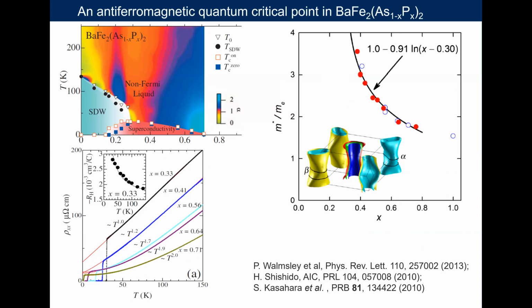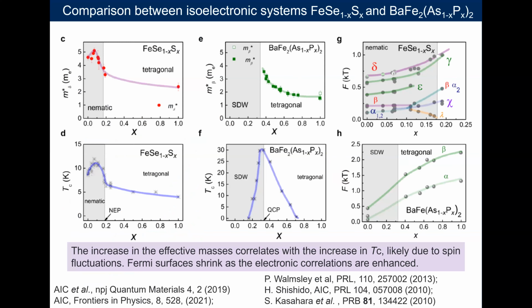In an antiferromagnetic system with quantum criticality, which is barium iron arsenide phosphorus, here one has a spin density wave suppressed and then the superconducting dome. And the quantum oscillations there show a very nice divergent behavior and linear resistivity. So these are the signatures which occur in the presence of strong critical spin fluctuations. What we found in our system with nematic order is very different from this case.